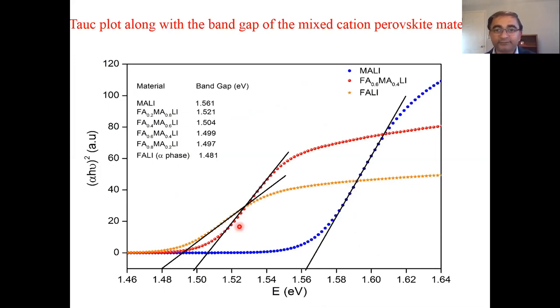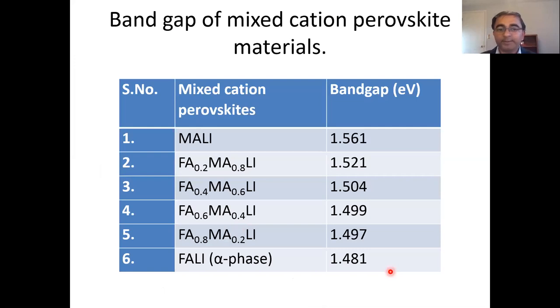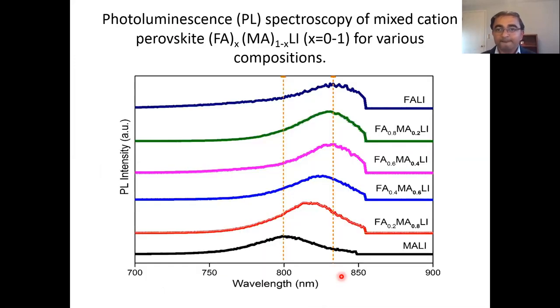You can see from here, this table shows the whole range of band gaps. This is photoluminescence, and from this PL, I also calculated the band gap, and it coincides very well with the band gap calculated by UV measurement. So this is another support to our UV measurement and the band gap calculations.